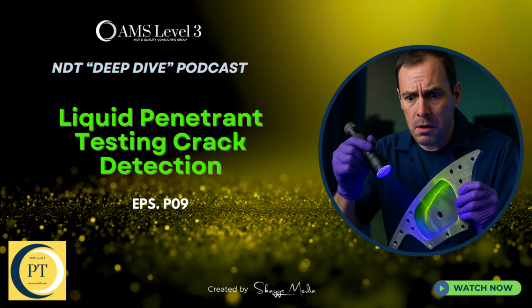Exactly. And second, as it does that, it spreads the indication out a bit on the surface, making it larger and easier to see, and it provides a high contrast background, usually white. So the tiny line of the crack becomes a slightly wider, more visible line on the white developer background. Precisely. Amplifies the signal. Is there a type of developer that's known for giving the sharpest, most sensitive results? Generally, the non-aqueous wet developer, that's a powder suspended in a volatile solvent carrier, is often cited as the most sensitive. Part of the reason is that the solvent itself can help dissolve and pull the penetrant out, assisting that bleed out action.